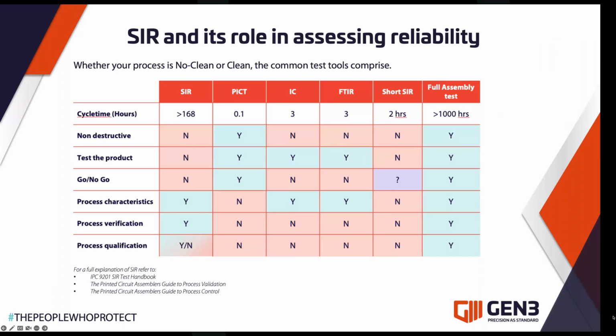Short SIR is really not very applicable. It's only potentially useful as a go, no-go type test. On the far left, we can see that the advantage of SIR is it can give you a process characterization, it can give you process verification, and really it's the only test that gives you a proper qualification because it's the only way to measure the material set. And it's very well complemented by PICT, which you can see we have the green boxes on the bottom of the table, and on PICT we have the green boxes on the top. For PICT, it's non-destructive, it can test the product, and it can produce a go, no-go type answer. And chemical tests like ion chromatography and FTIR are more useful for investigations when you've found you have a failure and you want to find the source. So that just helps to put in context how these different techniques work together.